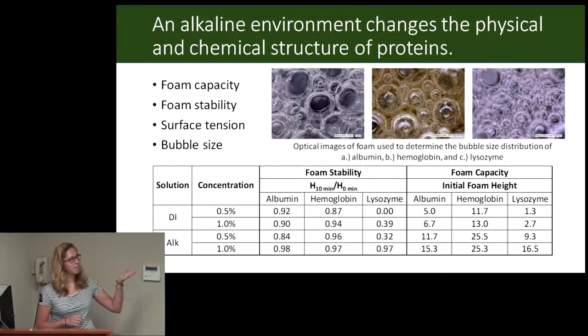Here you can see the proteins in the alkaline environment, where it lines up fairly decently with the stability capacity of the proteins. So we ran basic tests in these alkaline environments that are well known in distilled water and other materials, and compared them to our results in cement.